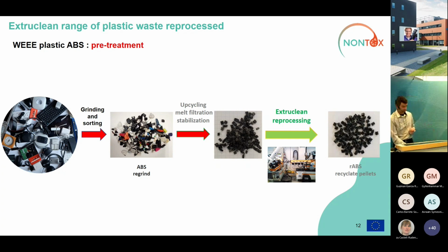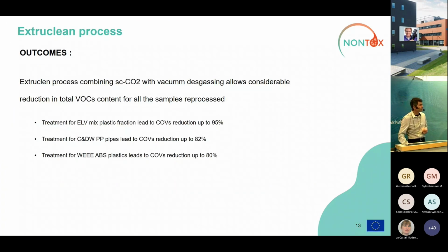So, as the main outcomes of our upgrading extrusion recycling process, we were able to assess that the Extruclean process that combines supercritical CO2 injection plus vacuum degassing allows a considerable reduction in the total VOC content for all the samples reprocessed, and also contributes to drastically reduce the disturbing odors and smells that are typical in plastic recyclates.